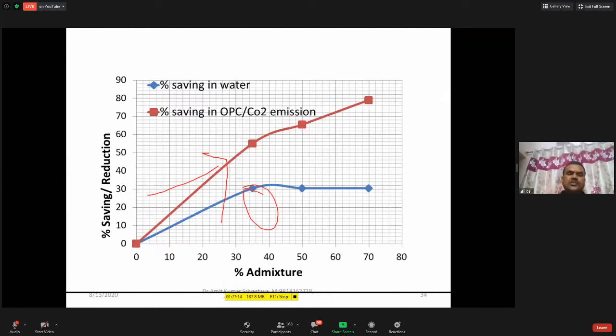Now, if I see in terms of the graph, the saving and reductions I am telling you are not only of carbon dioxide gas emissions, it is of the OPC cement also. I have averagely taken 1 kg of cement to 1 kg of carbon dioxide emission saving. If you see the red line, it is 0%. If you use chemical admixtures or mineral admixtures, it can go up to 80% reduction in the OPC requirement and 80% reduction in carbon dioxide gas emissions.